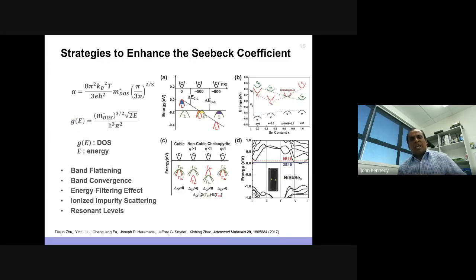So what are the strategies you can use to enhance the Seebeck coefficient? As I said, the Seebeck coefficient is squared, so it does play a bigger role. And you can see there, it completely depends on the density of states and the effective mass, m star. Because if you look at this formula, m star is the effective mass, which is due to band flattening and band convergence. I mean, I'm going too much into solid-state physics, but as you can see, you can still do a lot of theoretical calculation to understand whether we can do something about it.